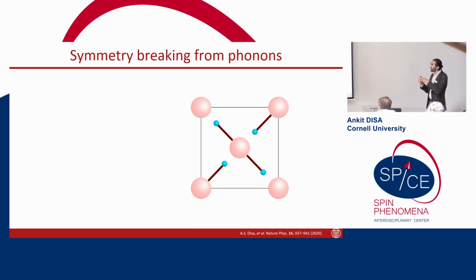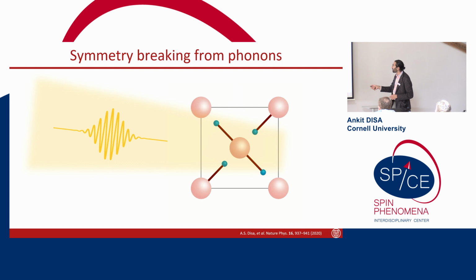This is going to be a DFT simulation of the dynamics. Again, this is the top view of the cobalt fluoride crystal structure. If we send a terahertz pulse which is resonant with one of the infrared active phonons, I'll show you that the lattice will distort along that Raman mode. Okay, so here comes the pulse. The vibrations of the infrared active mode are starting.